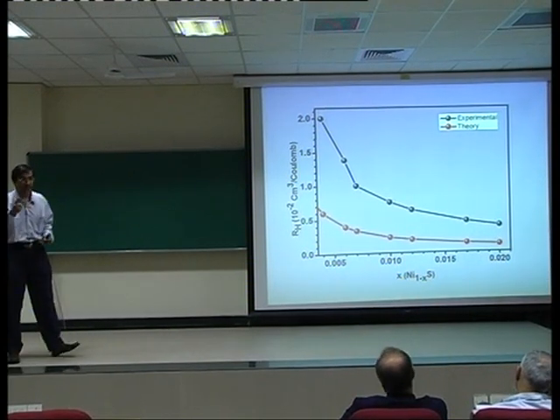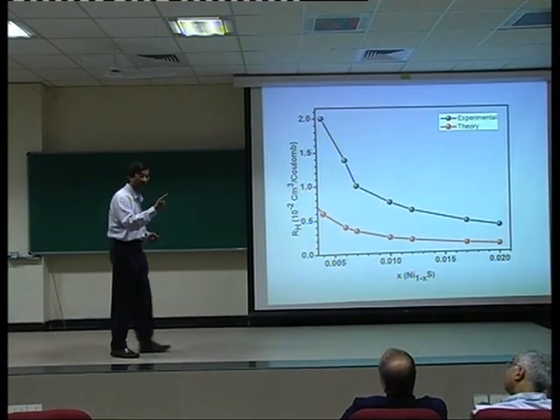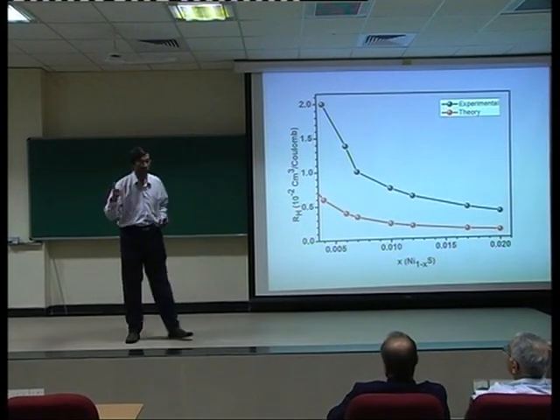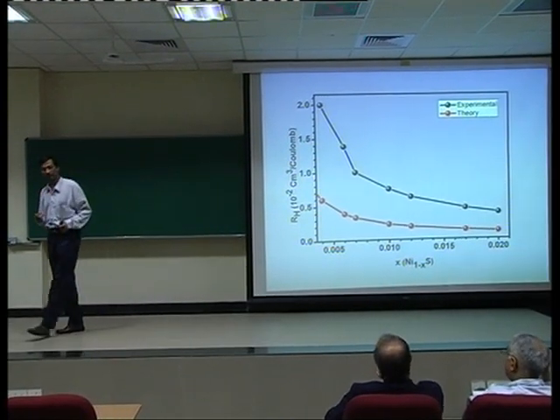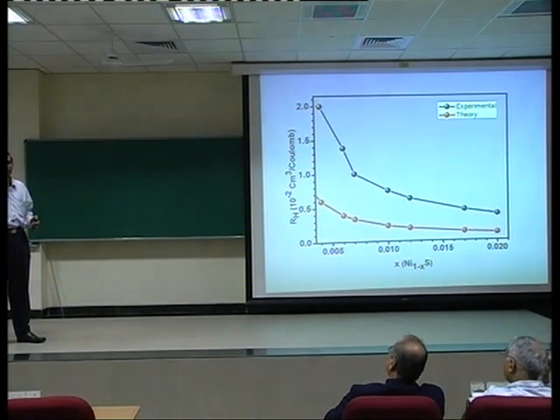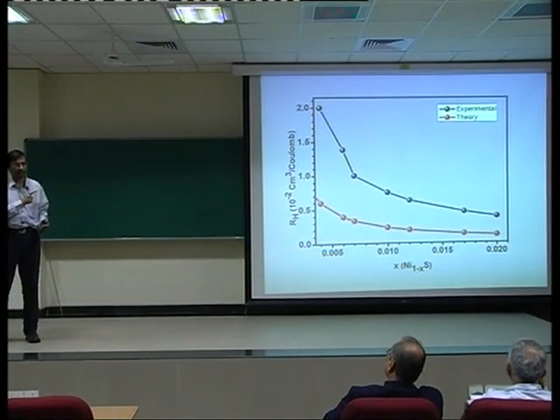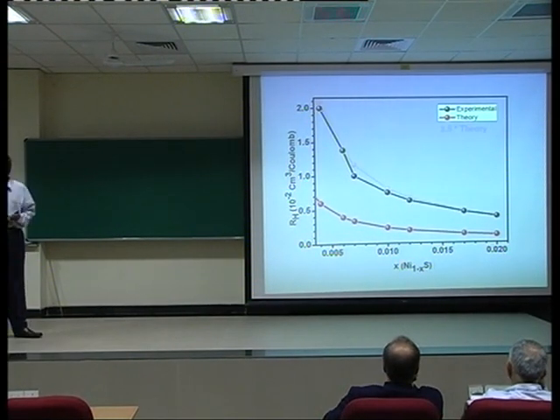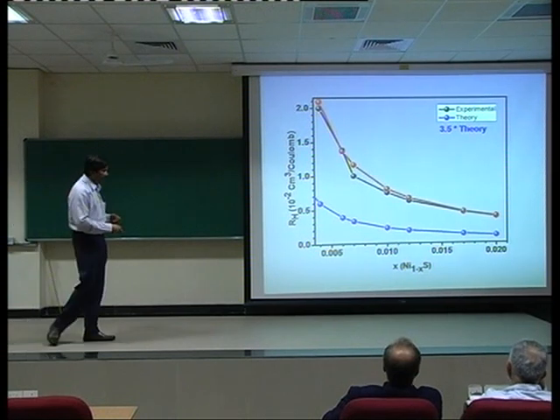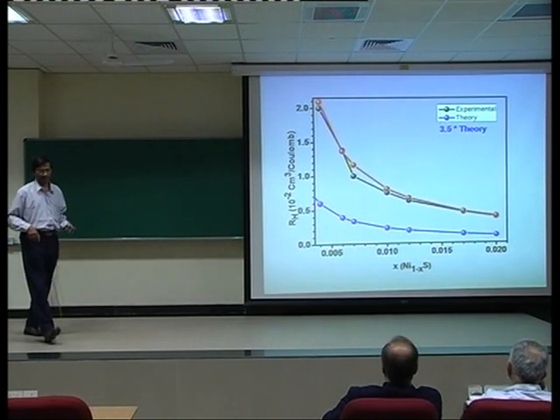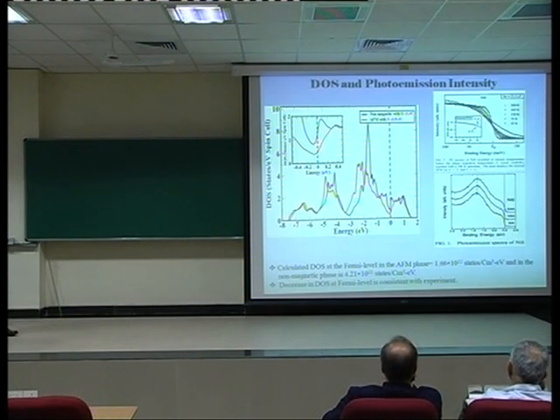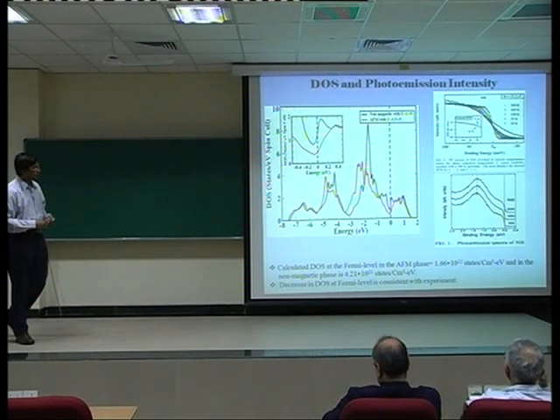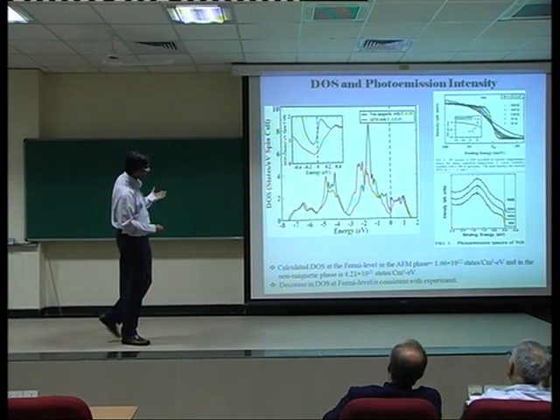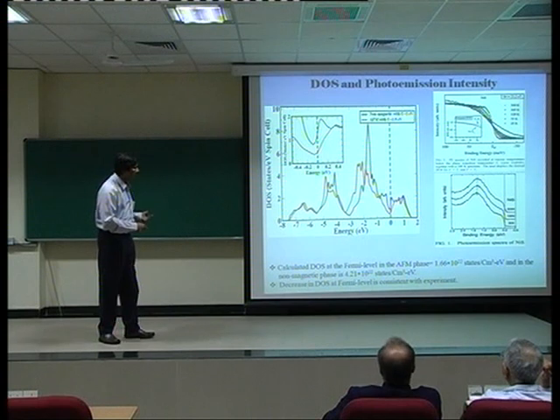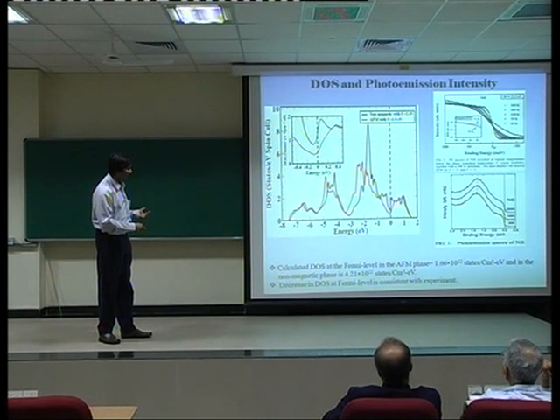Because after all, remember, mobility is a product of the conductivity and the Hall constant. So if I have to keep the mobility the same, since I divided by 3.5, I must multiply by 3.5, and I'll do that. And if I do that, I get that set of data as a function of x. Okay. Then one would say, fine, go and look at various spectroscopic data. This is the photoemission density of states, basically. You can see that this one is the antiferromagnetic metal, the red, and this is the non-magnetic metal.